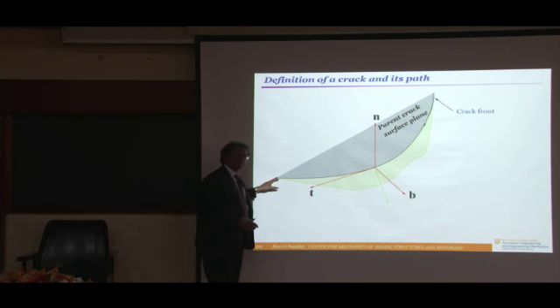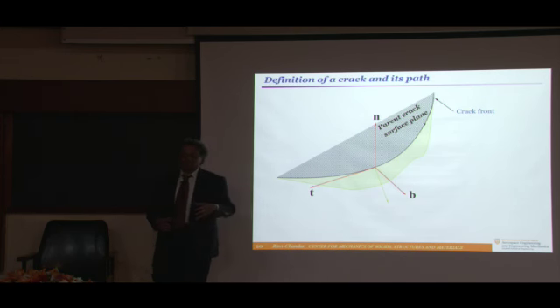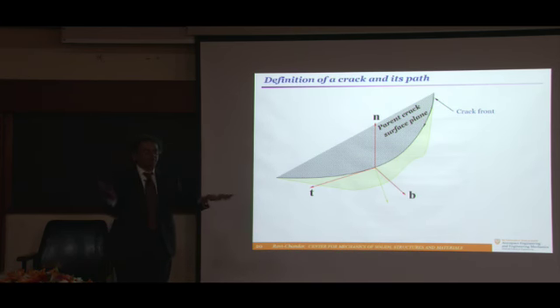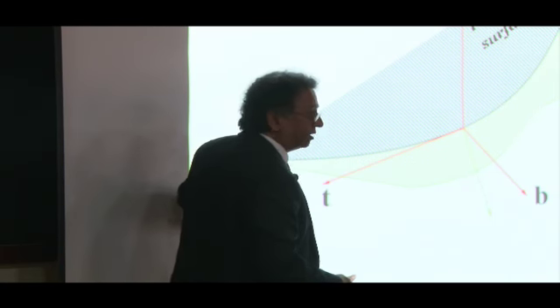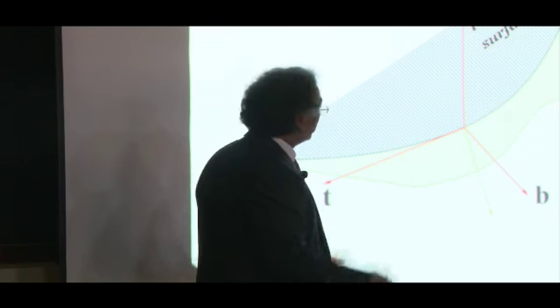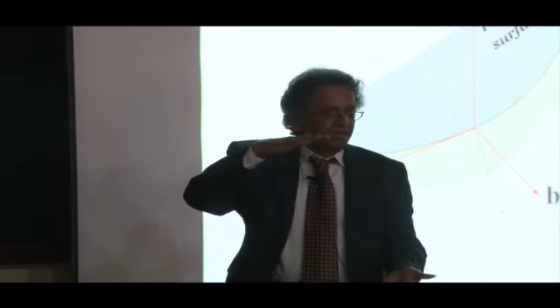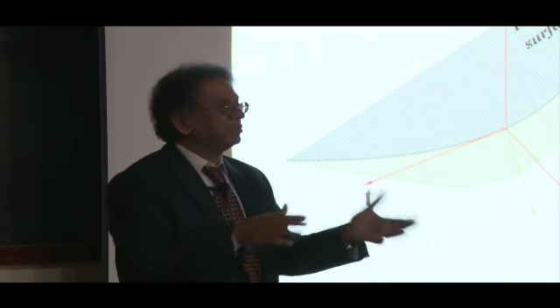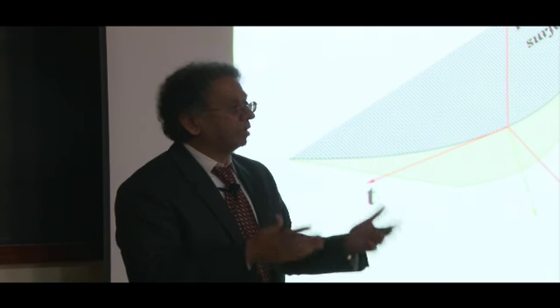If you now make a cut at some arbitrary location perpendicular to the T direction, you expose what happens in the NB plane, and we think that the crack is going to extend, move, increase in length along the NB plane. So it goes from here to there. So at every point along the crack front, if you prescribe what is the crack extension in the NB plane, you can recreate the crack front in the next step. It's an Eulerian description for a moving boundary.